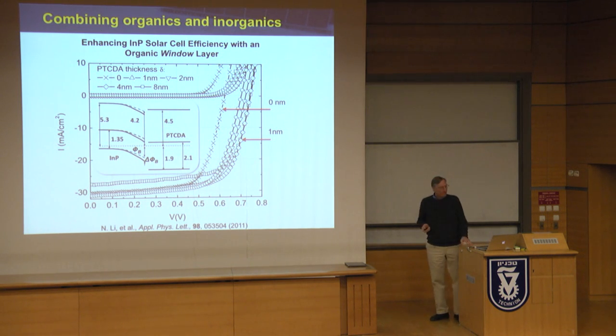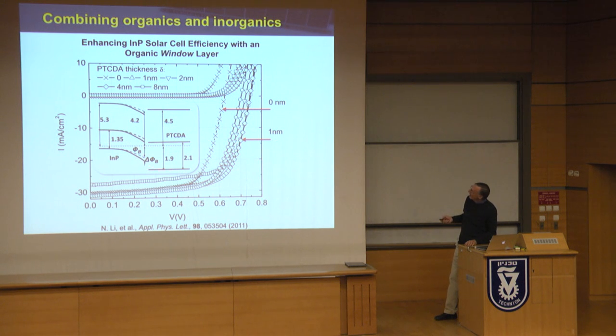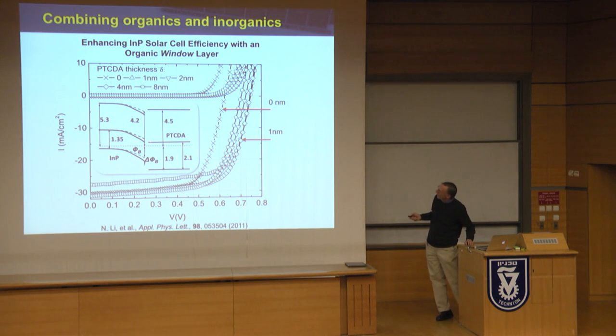My last view graph before the summary is just to show that if you put a little bit of organic, a very thin, just a couple of nanometers, onto the surface of an inorganic semiconductor, we call this a window layer, it increases. This is a Schottky barrier device. This has an ITO contact on it. We put this very thin PTCDA layer on top of it, and it increases the barrier height. And that increase in the barrier height increases the open circuit voltage. And we get about 2% more power conversion efficiency out of this indium phosphide cell, which is about 15%, just by putting on this very thin, basically free and quite environmentally robust PTCDA layer underneath the contact.